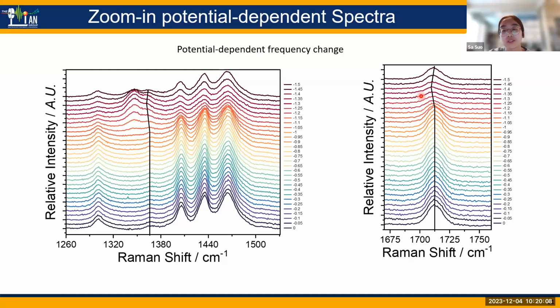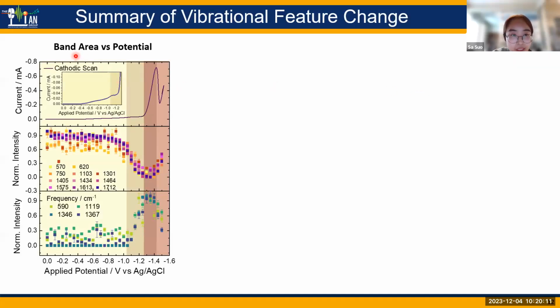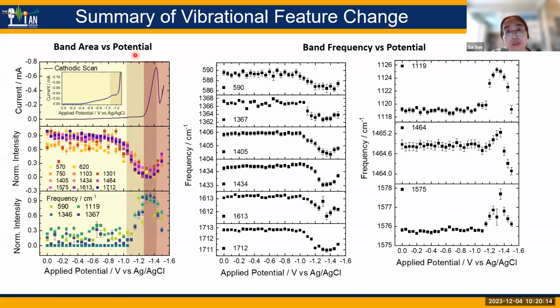So we basically saw the band area change as a function of potential, and also frequency change as a function of potential. I summarized basically all the peaks that we observed from Raman and grouped them by different trends. If we first look at the band area, we can see clearly there are two groups of peaks. One shows a plateau Raman intensity, and after the first reduction, the Raman intensity decreases and then recovers when the second reduction happens. And the other group of peaks has the opposite trend.